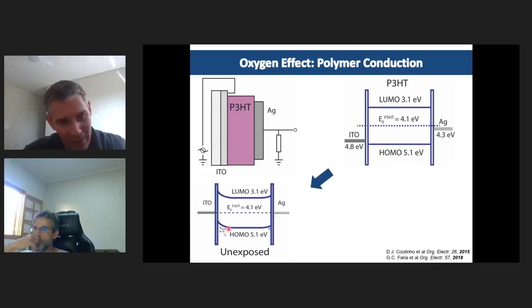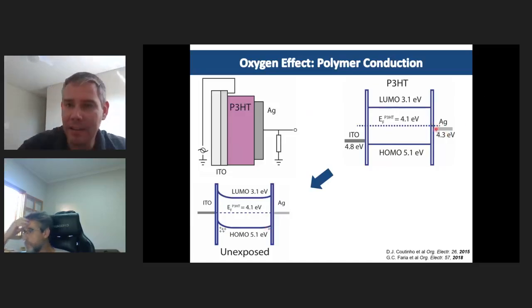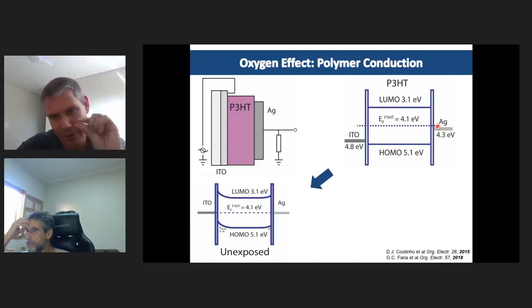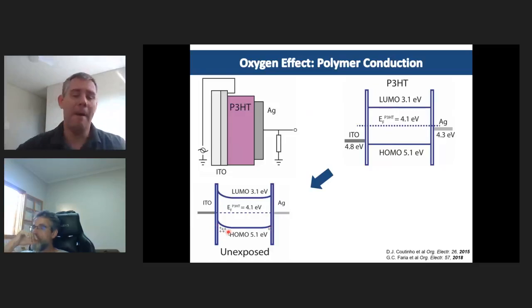So the ITO injects a lot of charge and creates a small reservoir of charges at the interface of the P3HT with the ITO, and bends a little bit the HOMO of the P3HT in that particular portion, creating a reservoir of charge that is proportional to the difference in energy between the Fermi level of P3HT and, of course, the work function of ITO. The same would actually happen at the silver, but because this gap is smaller, of course, the reservoir here is not as big as the one at the ITO, and therefore the ITO reservoir sort of dominates the process.